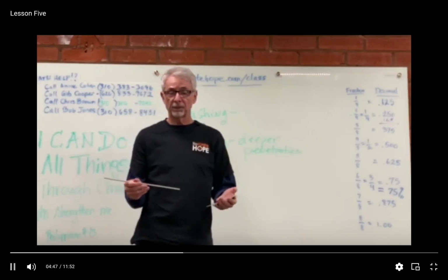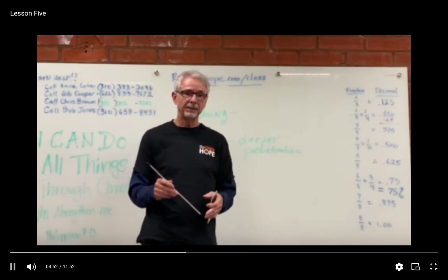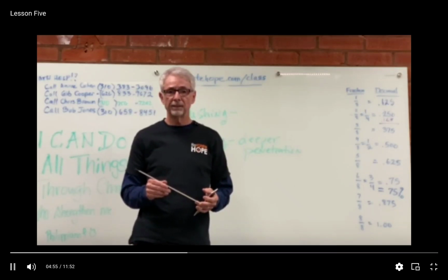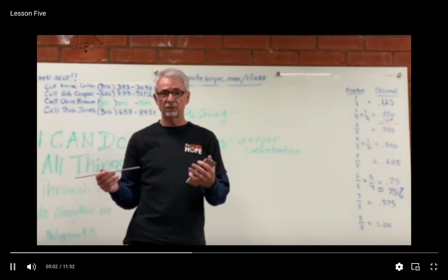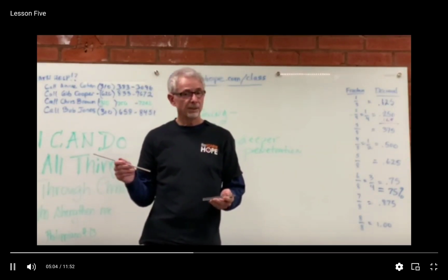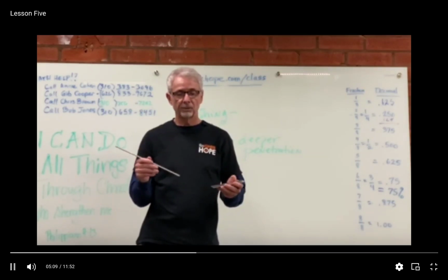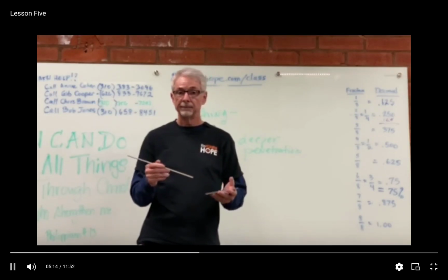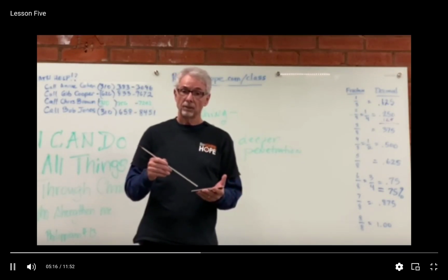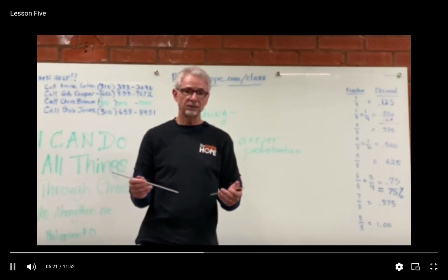On the other hand, if it's something where I want deeper penetration, then I might try pulling to get the bead to be a little bit more penetrated into the metal that I'm welding there. So that's a couple of differences there. Keep in mind too, certain processes, like I said before with TIG, you're almost always going to have to push the arc. You could in some exceptions do it otherwise, but you're almost always pushing with TIG. And if you're MIG welding aluminum, you have to push the arc. It does not work well pulling. So that's a couple of things to keep in mind there.